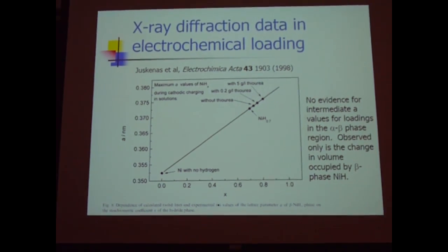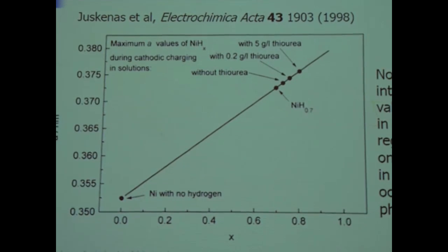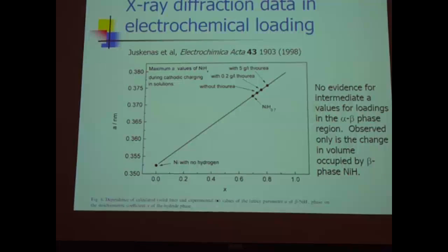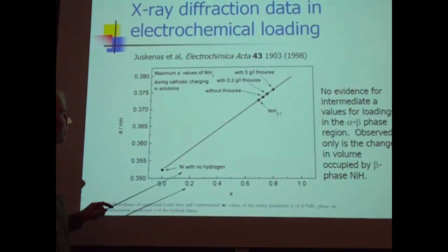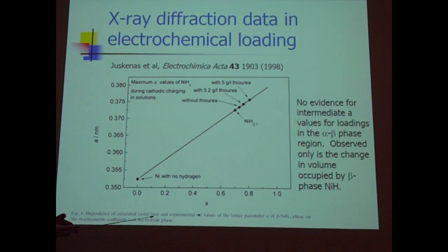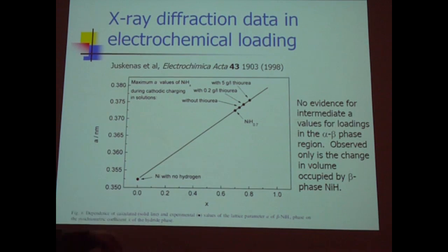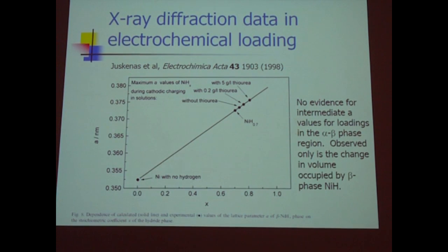Now, when you do load, hydrogen in nickel works differently than hydrogen in palladium. In hydrogen palladium at low loading, the hydrogen is randomly spaced. And as the loading gets higher, it is either randomly spaced or there's some other phase, perhaps involving hydrogen-hydrogen correlations. In nickel, what you see with X-ray observations is that if you have loading in the miscibility gap region, you don't see a lattice constant that would correspond to the miscibility gap loading. What you see is either nickel with no hydrogen, or a lattice constant corresponding to the hydrogen at high loading. So, for example, how do you explain this?